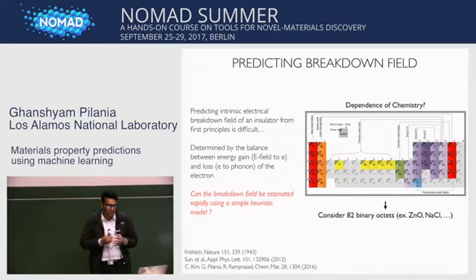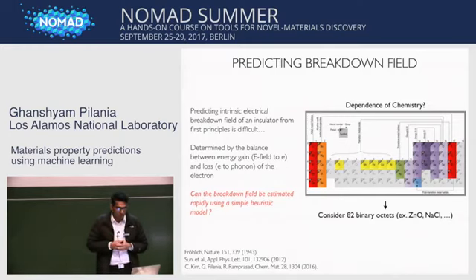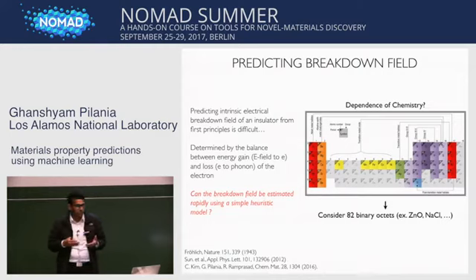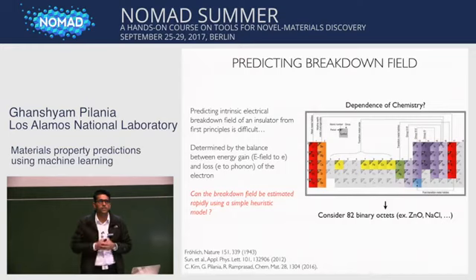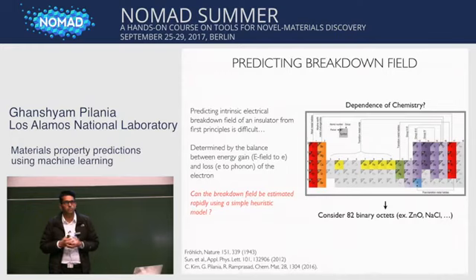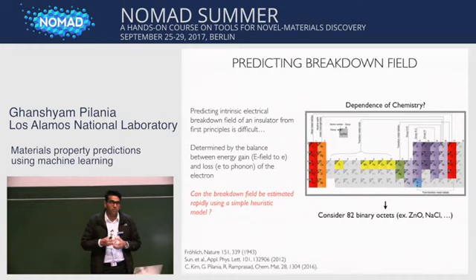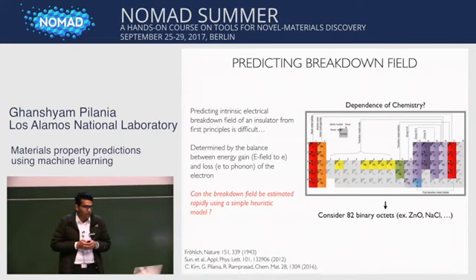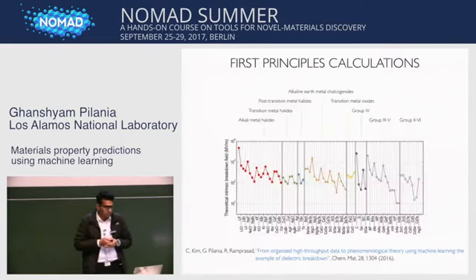So to test this, we created a database of 82 binary octets from first principles. It was very laborious and took us a long time. And once we have this breakdown field strength data for 82 binary compounds, we actually validate these results against experimentally available data. For all of them, experimental data is not available, but for a dozen or so, reliable experimental results are available, and we use that to validate our computed results. And after that, let me show you the final results.